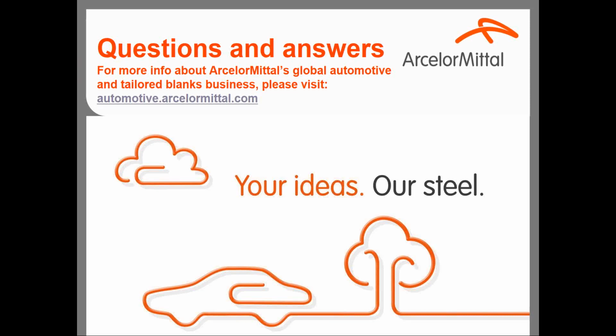Okay, thanks. And actually, Luciano, this is a question for you. What's the advantage of laser welded blanks versus partial hardening? Yeah, good question. Partial hardening is well used today in the market, and is a good competitive solution to laser welded blank. I would say there are two advantages. The first is what we can call robustness. The heat affected zone in laser welded blank is well controlled and is really narrow and limited to the weld seam.